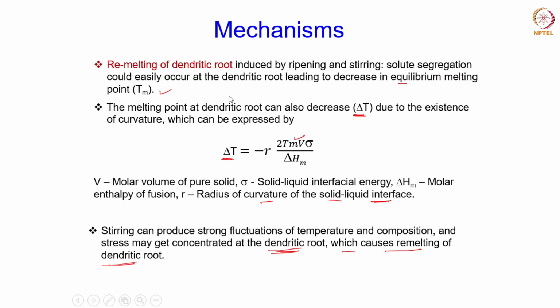This is another mechanism that we talked about, the remelting of the dendritic roots, which occurs due to solute segregation. Solute segregation leads to a decrease in the melting point locally, and this would cause the remelting of the dendrite roots because the solute segregation primarily occurs near the roots. Therefore, locally in those places the melting point would decrease and it would lead to the remelting of the dendrite roots, which in turn will lead to their breakage, giving rise to more nuclei in the melt.